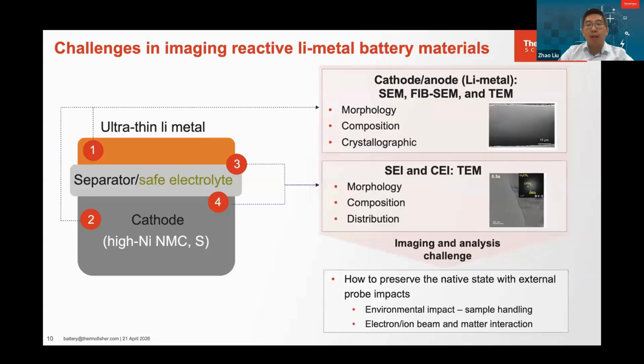If you look at one and two, the cathode and anode side, what you're interested in is the morphology itself, the composition, or the crystallographic information on both sides of the materials. The techniques used in the electron microscope part cover SEM, FIB, and TEM. Then if you look at the interfaces, three and four, corresponding to the solid electrolyte interface and the cathode electrolyte interface, the major characterization method is the transmission electron microscope, and the features of interest include the morphology, composition, and distribution.